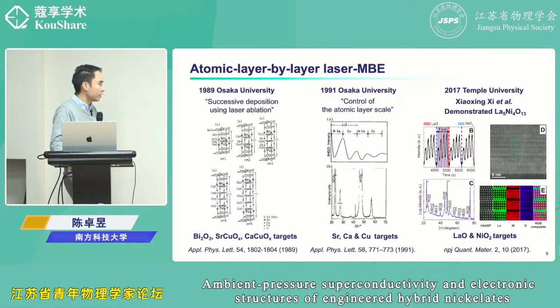Ruddlesden-Popper nickelate phases. And the difficulty of using this, the reason that this is not so mainstream, maybe is because the control is actually quite difficult to do because you need a very good automation to really do switching this target, and also the degradation of the target is also difficult to maintain.